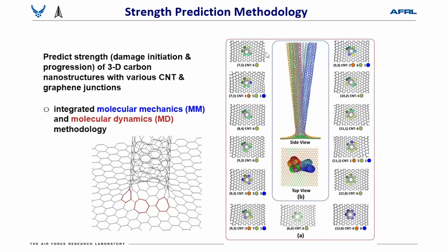So we have done the strength prediction with this surface topology optimization, and that is done adapting the tools we have developed, molecular mechanics and molecular dynamics. Molecular mechanics in this case is similar to molecular dynamics, but we took away the dynamics part just to focus on the static problem. And combining these two, we not only can create the junction, but also analyze the strength. This is the case for graphene with a carbon nanotube junction.